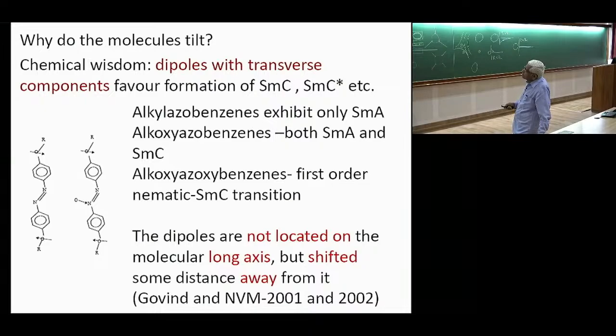See, if you look at the molecules in which it tilts, by the way, if you take just a spherocylinder and tilt, the cross section increases, the molecular cross section. In fact, because of this, the entropy decreases. So the hard rod interaction will never allow tilting. So it should be some attractive interaction which is responsible for the tilting. The question is which one?